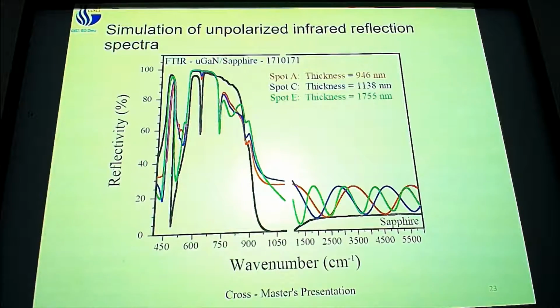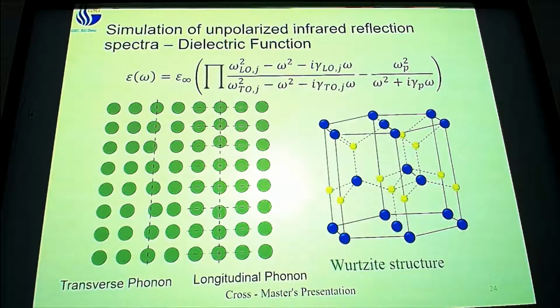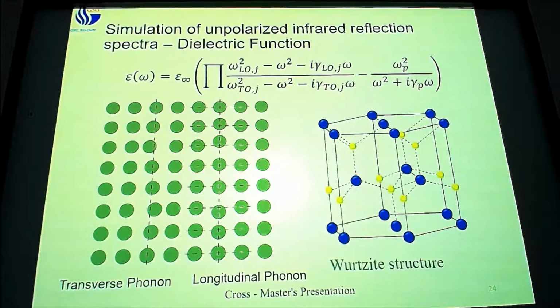Can I simulate the reflectance that I get from the FTIR in order to talk about my crystal structure, and about the charges that I have moving around in my crystal structure? So the first thing we want to talk about, going back to this picture, is what's going on here. In order to talk about this, I need to talk about the dielectric function. If the dielectric function was more or less constant, I wouldn't see this. I shouldn't say smooth, sorry. Smooth is not a good word. It's a mathematical word that means a lot more than I think it means. If it was well behaved and kind of flat like the rest of it, I would just have these reflectance fringes all the way across. But because it isn't, because I have these phonon frequencies and this plasma frequency, that changes the entire way that my sample reflects light. That's what I'm looking at.